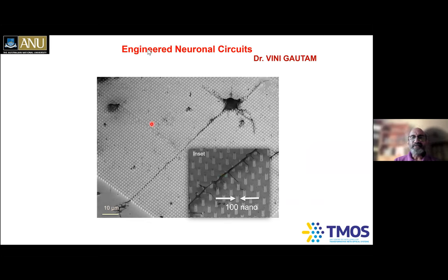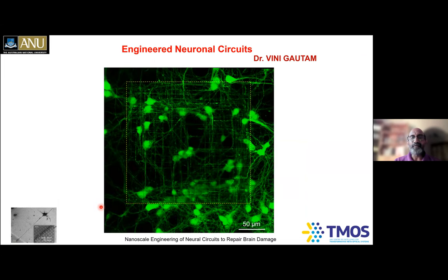In this box is where the nanowires are. If you put these green blocks of neuronal cell bodies, the soma, you can see that the neurites and axons follow these square patterns. If the neurons are grown on the plain indium phosphide substrate outside, you can see these neurons making random connections. There's no pattern like this square pattern, which you can create here.